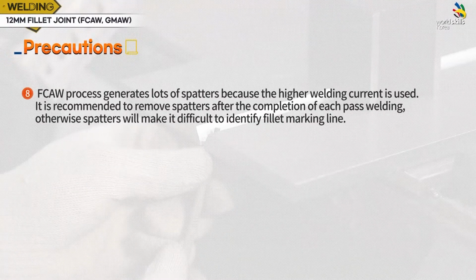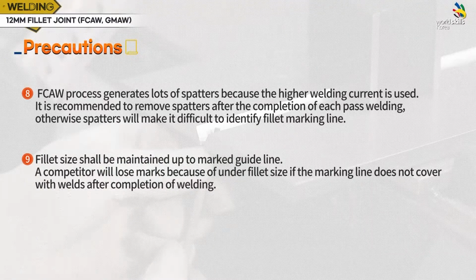FCAW process generates lots of spatters because the higher welding current is used. It is recommended to remove spatters after the completion of each pass welding. Otherwise, spatters will make it difficult to identify fillet marking line. Fillet size shall be maintained up to marked guideline. If the fillet welding size remains short even after the welding is complete, a point will be deducted due to the shortage of the length.